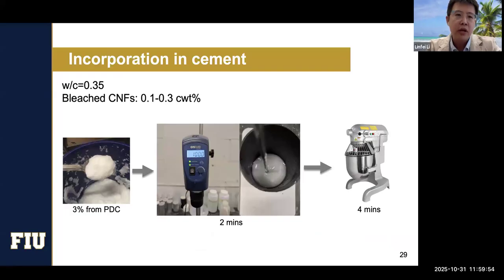And we started incorporating that in the cement. We just did one mix design at this moment, with a water cement ratio of 0.35, but we use three different dosages of CNF, from 0.1% cement weight to 0.3% cement weight, because for nanomaterials, apparently you don't want to add too much. The first picture shows the about 3% cellulose nanofiber we're getting originally.